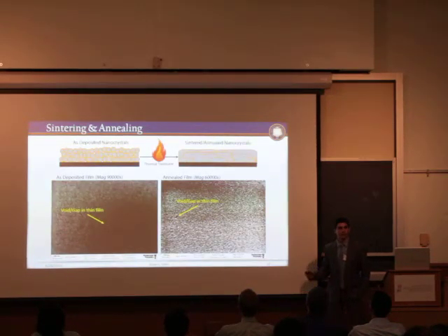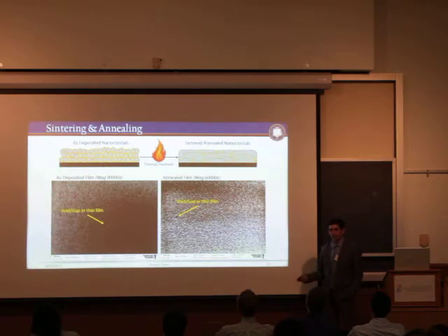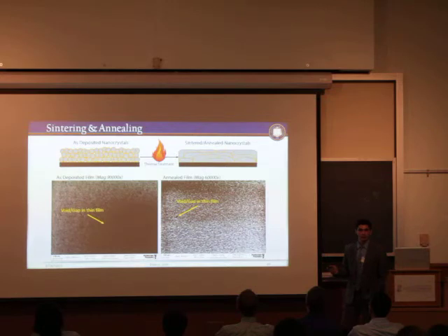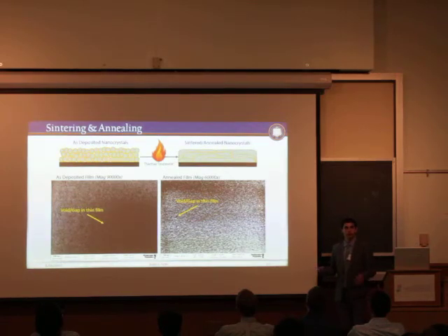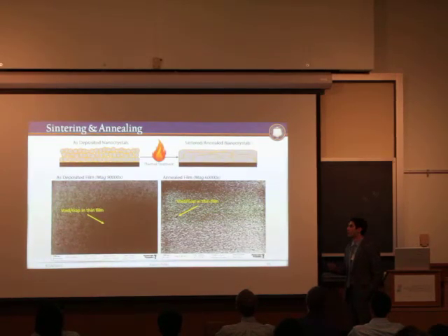And then now we have these as-deposited films. We thermally heat or treat them, and we start to get these larger grains and domain growths, which are really important for electrical conductivity and performance and other such things. These are scanning electron microscope images, so this is a different technique than previous. This is 90,000 times magnification, this is only 60,000 times. As deposited, you can't even make out how small these nanocrystals are, but you start to see these large domains at a lower magnification. So this thermal annealing really grows these crystals into larger sizes, into these larger annealed particles.